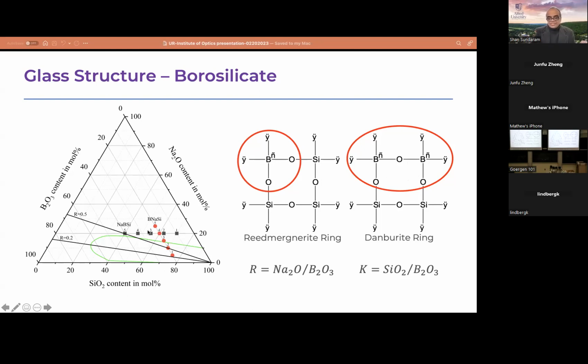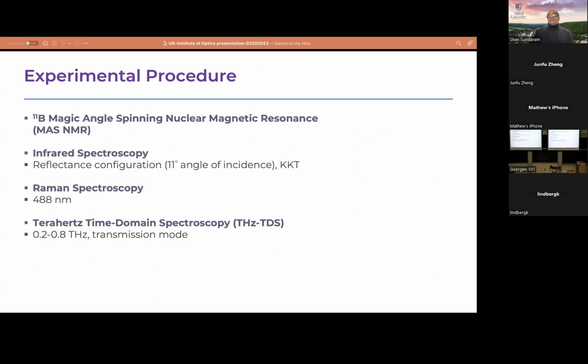And what we did is we selected these compositions and made these glasses in our lab. You can see the red dots and the black squares. We made them in our own lab, starting with high purity chemicals, mixed them, melted, quenched, solidified, annealed, and prepared our samples. And then we measured whatever we wanted to measure. As you recall, I showed you in our terahertz spectra, we are not seeing resonance because we don't expect to see structural responses in that frequency range, but we can measure optical properties directly. So we used other well-established vibrational spectroscopic techniques to track the structural changes, and then we correlate them to the terahertz properties we are measuring in these glasses.